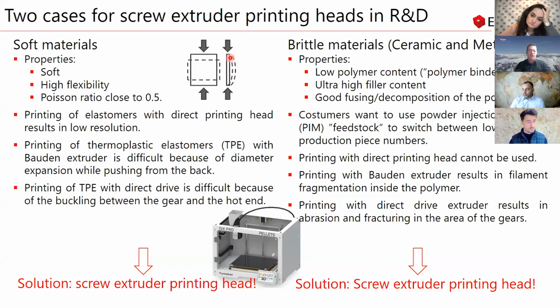So that means the stiffness is not enough so that you can really transfer the load to the filament, which needs to work like a piston in a piston extrusion to push the material through the hot end. And these are the main reasons why filament printers have a huge limitation, and that's the reason why the screw extruder can take over these materials. However, we have to say that still now the resolution for the screw extruder printing head is a little bit lower at the moment, but nevertheless we can really print materials which are not possible to print with a direct drive.